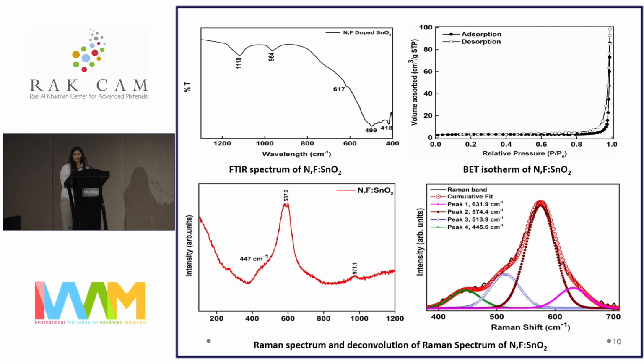FTIR, BET, and Raman spectra were carried out to know the bonding behavior, and to know the hysteresis loop for the surface area, which was approximately 102.22 meters square per gram. And the Raman spectrum depicted the presence of oxygen vacancies, as we can see from the deconvoluted band spectra.